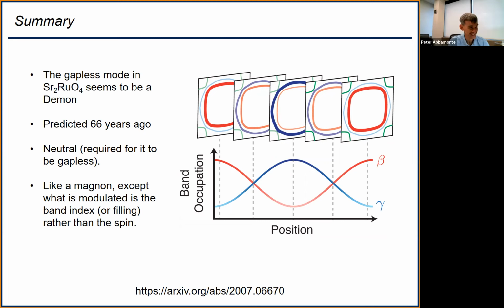No. In our defense, we haven't even published this yet, so we haven't worked on whether the experiment is actually possible. We can't do hydrostatic pressure for obvious reasons. You can't get the beam in and out, but uniaxial pressure is possible. People have shown uniaxial pressure can really tune TC and so on. So what we would have to do is build a custom sample stage, put one of these Clifford Hicks kind of cells on it, and then apply strain. And there's a bunch of issues of stray fields and things we'd have to straighten out. I think if Ali gets a faculty job, that'd be a great assistant professor proposal for him.